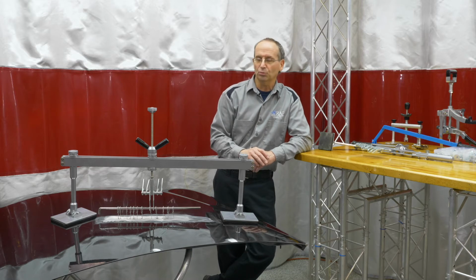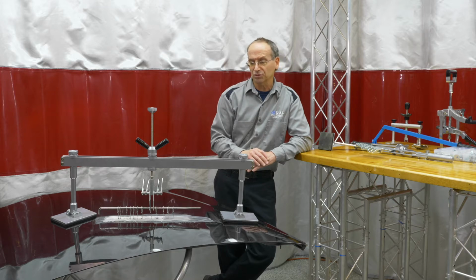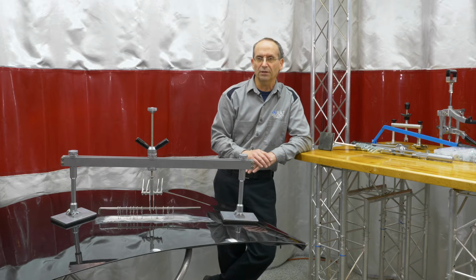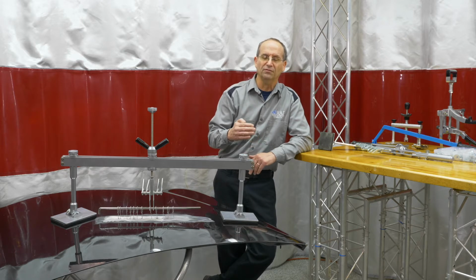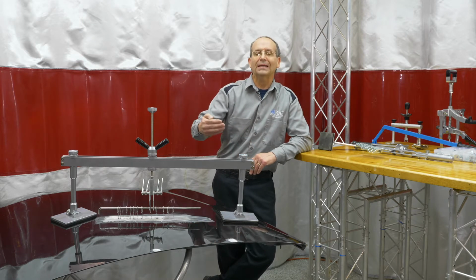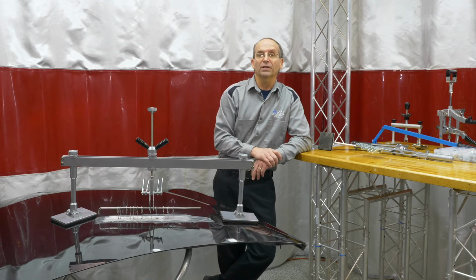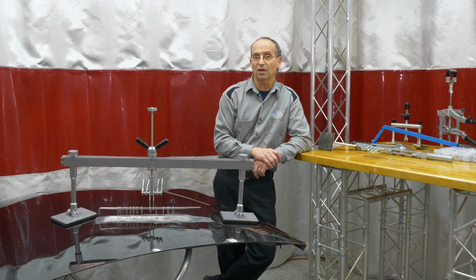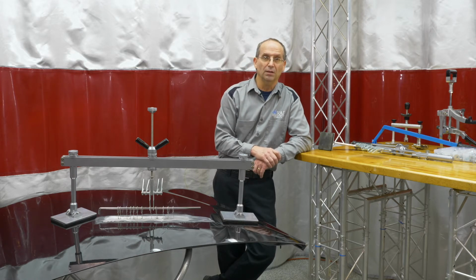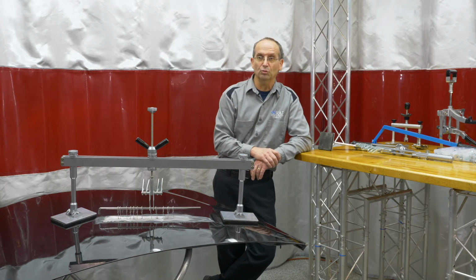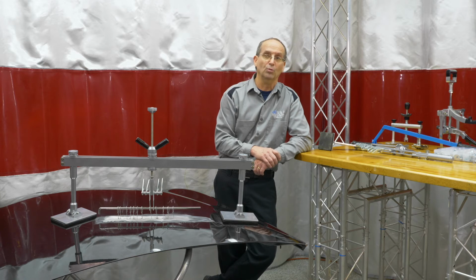General guideline is you really don't want to get past about 400 degrees on aluminum. Audi actually has their limit set around 320. The problem is when you start getting it up around 400, it's very easy for that heat to get out of control, get up to the point where when it gets too hot, it actually anneals the aluminum. It actually takes the tensile strength out of the aluminum. Once you overheat aluminum, you cannot retemper it again. So you have to have a little caution when you're doing it. Heat is your friend for straightening. Heat can also be your enemy if you don't use it correctly.